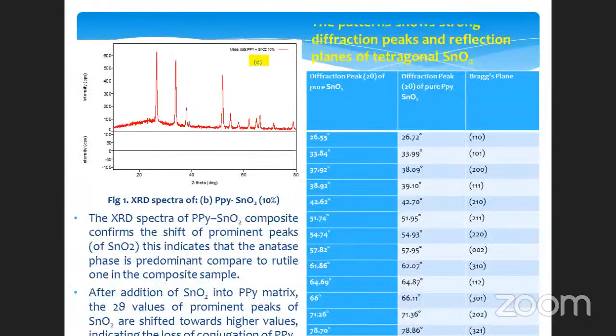Next, please. This is again a composite formed with the help of SnO2. And this spectra shows the diffraction peaks of SnO2. You can see this is 26 degree. It is shifted to 26.72 degree for the composite. And all the peaks are shifted toward the higher thetas. This shifting of prominent peaks towards higher values in XRD indicates that there is loss of conjugation of SnO2 with the conducting polymer polypyrrole. Next, please.